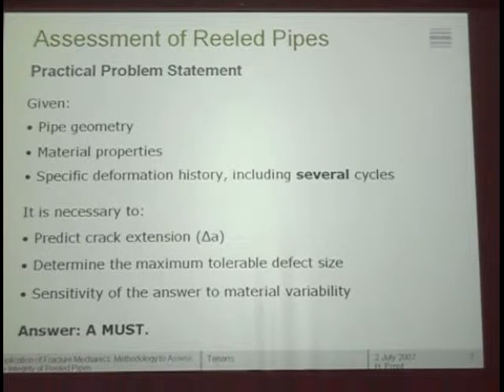Okay, so the problem that we have, and this is all we have to resolve here, is: given the pipe geometry, that is radius, thickness, and so on, material properties, all the material properties you want, and a specific deformation history, including several cycles. And I repeat several, because I showed you just 2, but there are the so-called contingency installation procedures. That is, if you already have the pipe in the ocean, maybe there are some bad weather conditions, so you have to retrieve the line through the 2 wheels back again, so that puts not just 2 deformation cycles, but several. Not that many, say about 10 to 12, no more than that, but still it's much more than 2 obviously.